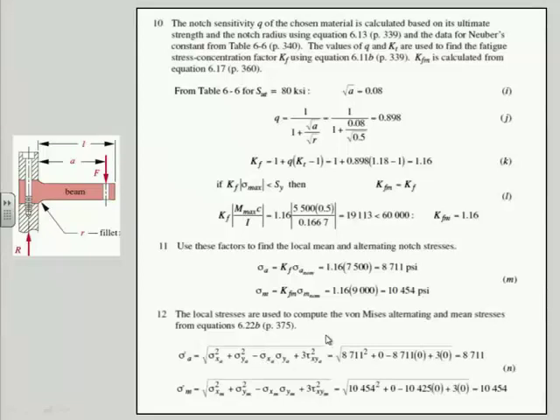Now, I'm violating my own tenets here a little bit. I'm not bothering to calculate the principal stresses in this example. There are equations, and I think it's 6.22, so I don't reveal them until we get into Chapter 6. But I can calculate the von Mises stress in terms of the applied stresses: sigma xa squared, minus sigma xa sigma ya, plus sigma ya squared, plus 3 tau xya squared. We don't have any sigma y in this particular case, so those terms are 0. So we just have the sigma x squared sub a and the 3 tau xy squared sub a. I don't even have that in this case, so there's no torsion. So I really just have this term, and the von Mises is going to be equal to my applied stress. I have a uniaxial stress case here, much like the tensile tester, right? And in those cases, the von Mises is equal to the normal stress.